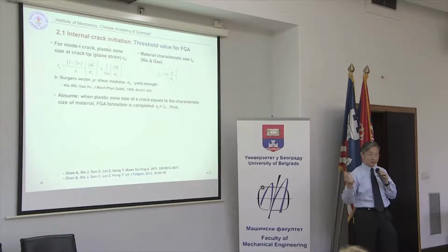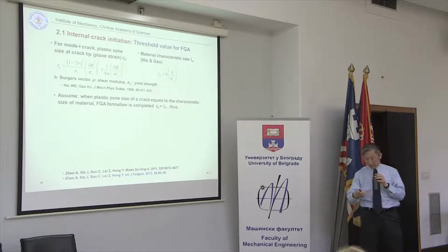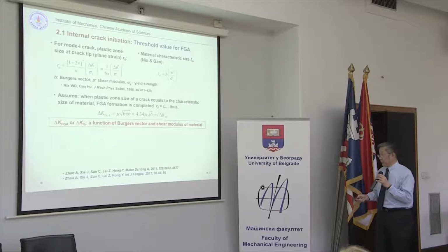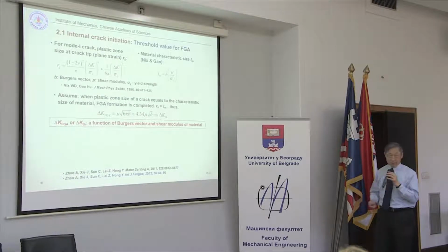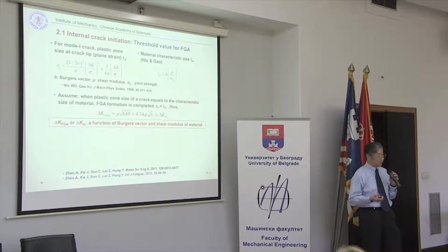But of course, you may argue about this type of assumption. But we just made this assumption, and then we are able to get this expression to show the value of delta K FGA is just a function of shear modulus and Burgers vector of the material. So it's very simple and very clear to tell us what will be connected with this very important variable responsible for crack initiation.